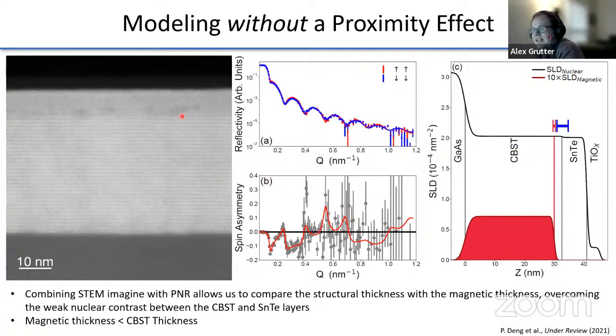So what we did was get really high resolution transmission electron microscopy and constrain the thicknesses of the layers using that. That's what gives you this blue bar right here. These are the 95% confidence intervals on where the interface between the two layers ought to be. Then we can get the magnetic thickness very precisely from the neutron reflectivity, and the red line here is telling us where the magnetized region stops. Because these don't overlap, the magnetization doesn't extend into the tin telluride, but it really took combining TEM imaging with neutron reflectometry to figure this out.